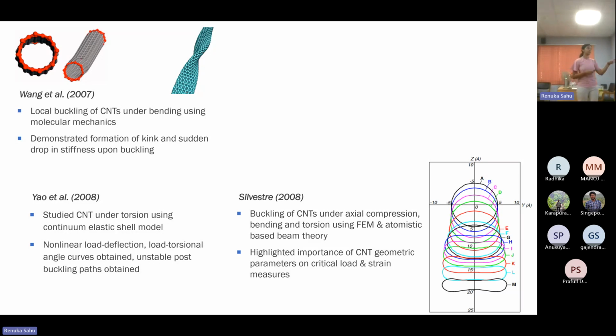Silvestre did a study of buckling of CNTs under axial compression, bending and torsion using FEM and atomistic beam-based theory. They highlighted the importance of CNT geometric parameters, the radius and thickness, on the critical load and strain measures. This plot here is derived from that paper.